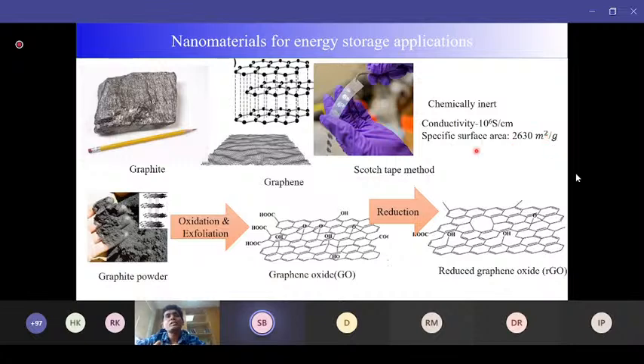Per unit gram of graphene, the surface area is 2,630 meters squared. That means with 1 gram of graphene, you can cover nearly 1 football ground. And it has a very high conductivity, up to 10 to the power 6 Siemens per centimeter, and it is chemically inert, so it is a more stable form.